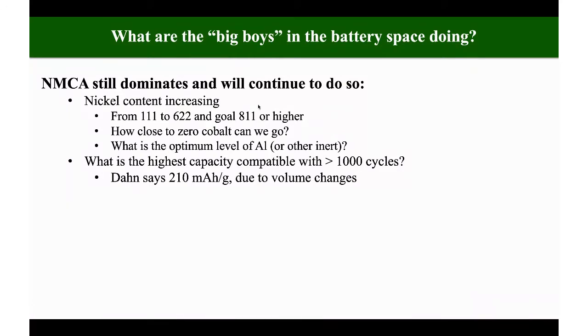The challenge here, the 80% nickel is much more reactive. The material itself has to be handled in an inert environment like a dry room. You can't handle it in an open lab, even in California. So the question today is, how low in cobalt can we go? And clearly, I think we can probably get to 5% without any trouble. Question is, can we get down to 1 or 2%? And all these materials have a certain amount of aluminum in there. Tesla was using about 5%. Can we get down to 1%? And there are indications we can. Every bit of aluminum in there, you cut the energy density. And there are indications that other materials like magnesium or manganese will be just as effective.